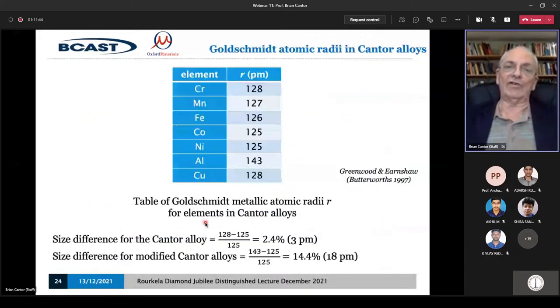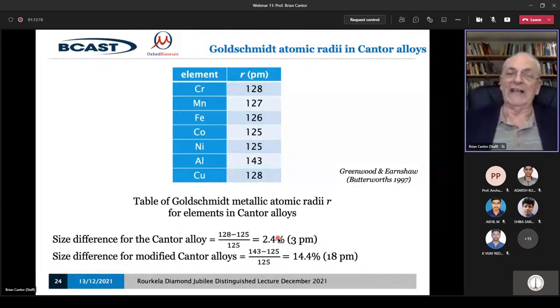What about the local strains? Well, the simplest way to look at that is just to look at the size of the atoms in their normal pure state. This is the size called the Goldschmidt radii. If we take the top five here, that's the 5 components in the original Cantor alloy, and these are their atomic radii. They vary by about 3 picometers. So the size difference is about 3 picometers, which corresponds to about 2.5% variation. So we would expect to find up to about 2.5% local distortion. Now, this is very simplistic. The atoms will change their size locally. It won't be the same as in the pure material.